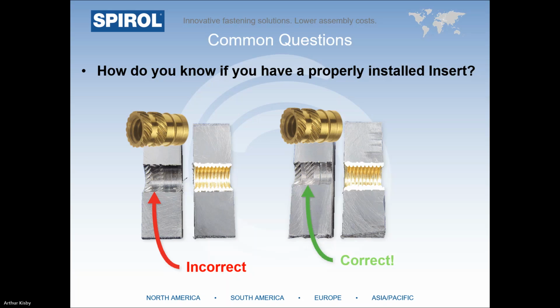So how do you know if you have a properly installed insert? This is most definitely a destructive test that you need to perform, maybe even a little barbaric. We would literally take a hacksaw and section the plastic component with the installed insert in half, then pop the sectioned insert out of the hole and ensure that the features of the insert are mirrored in the plastic, as shown in the image on the right. It's extremely important to ensure proper plastic flow into the features of the insert, as this dictates the torque and pull-out performance you achieve. As you can see on the left, the plastic did not sufficiently flow into the retention features, which will result in low insert performance.